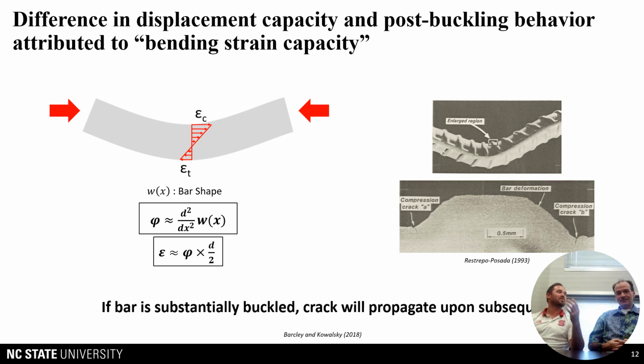So what's the difference? Why is there this difference? And in reviewing it, this paper on the right was from back in 1993, I think, and really identifying that when a bar buckles, they did a cross section through this. We see there are these micro cracks that occur at the base of the ribs. So I think the thought was, maybe there's something in terms of the actual bending strain, as they called it in this paper, and we ended up calling it as well, that's related to how the tensile strength is affected.